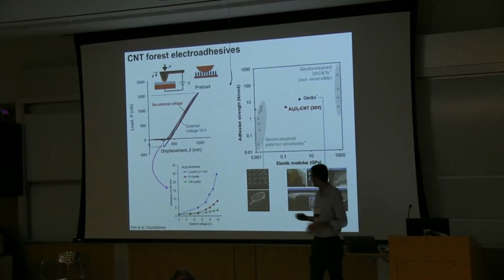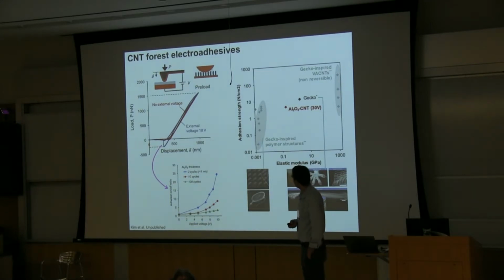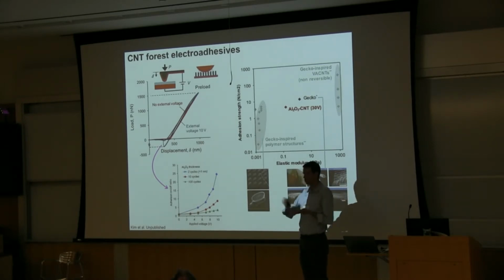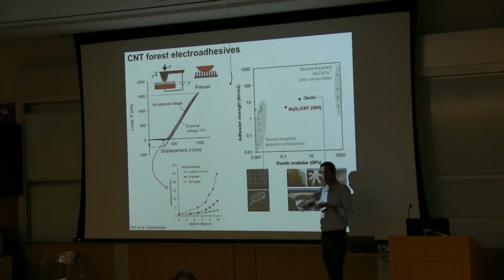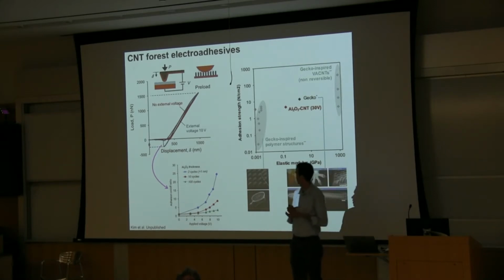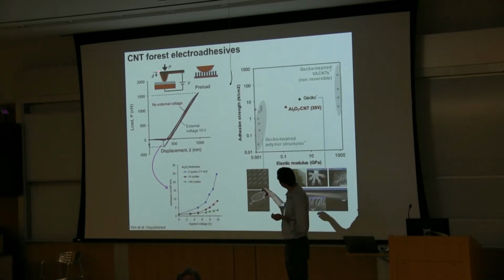So how this all relates is just this slide, and the fact that we've started to study how to use these nanotube surfaces as what I'll call electroadhesives, which is a term that has been used to describe the use of electrostatic voltage to apply force to materials. And here's an experiment where we take an AFM tip with a conductive coating on it and apply a potential across a nanotube forest where the nanotubes are coated with a thin dielectric.